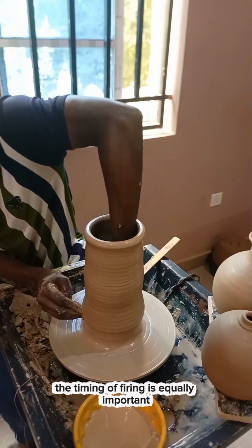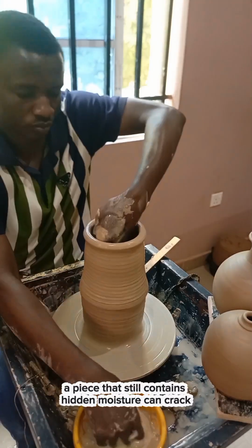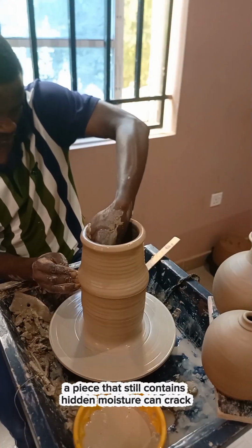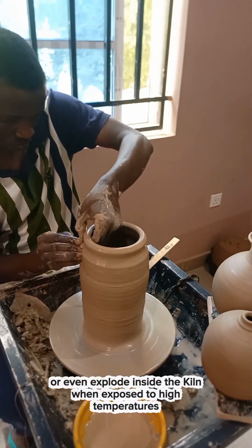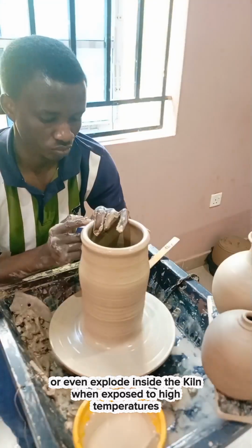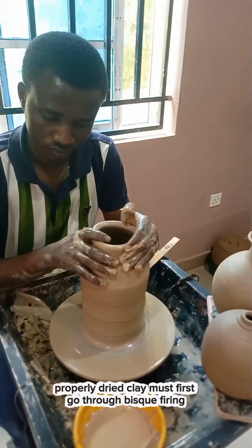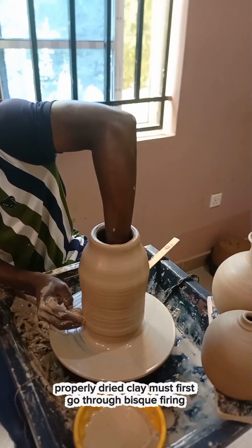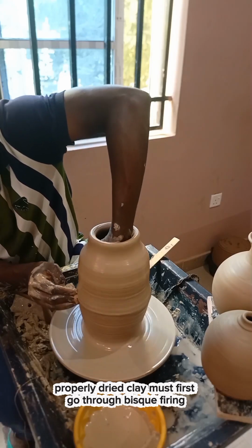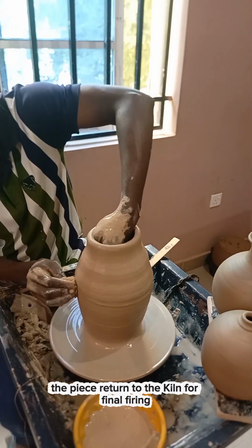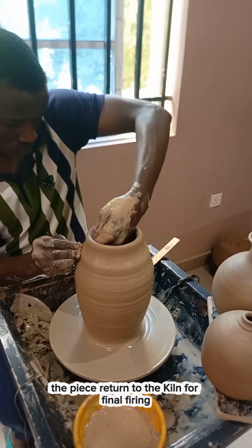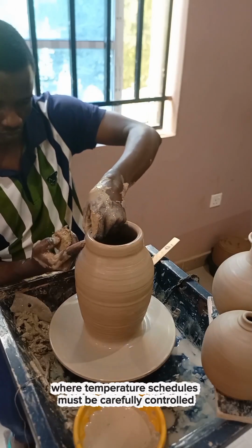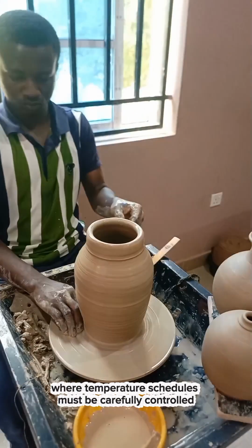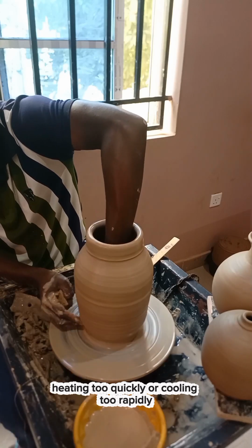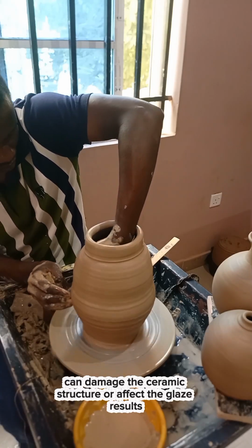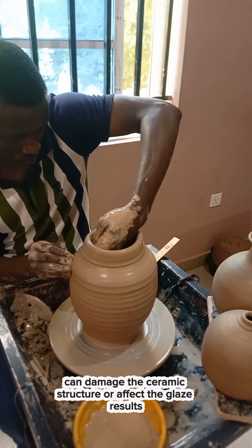The timing of firing is equally important. A piece that still contains hidden moisture can crack or even explode inside the kiln when exposed to high temperatures. Properly dried clay must first go through bisque firing. Then, after glaze application, the piece is returned to the kiln for final firing, where temperature schedules must be carefully controlled. Heating too quickly or cooling too rapidly can damage the ceramic structure or affect the glaze results.